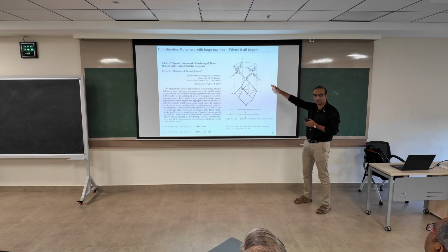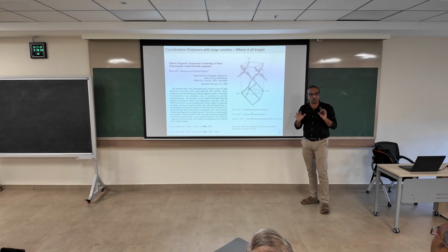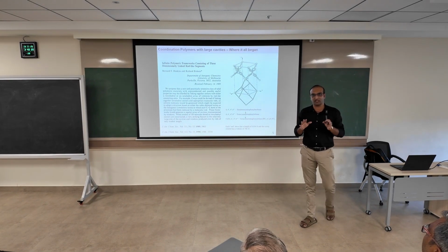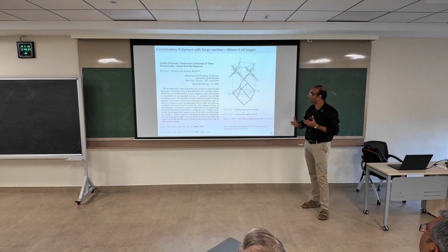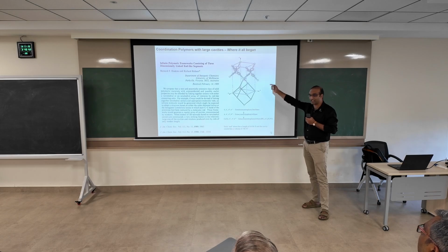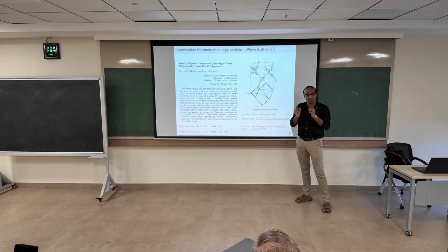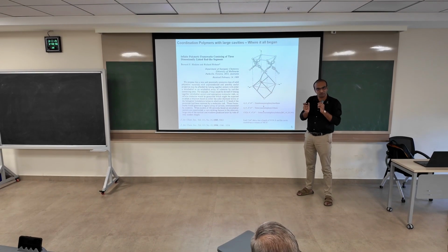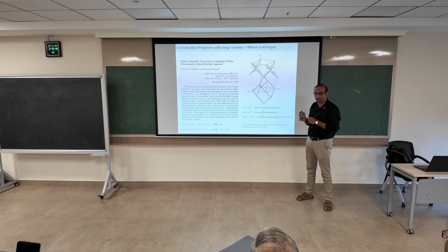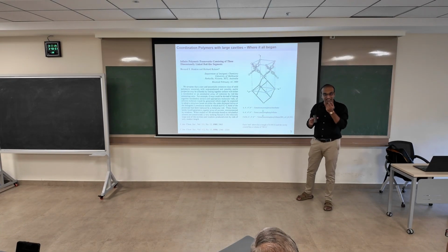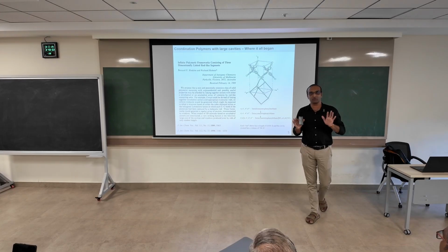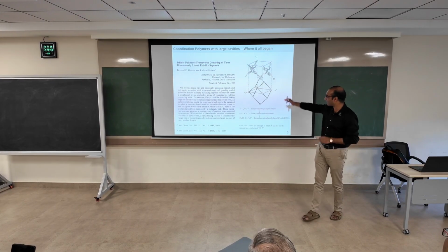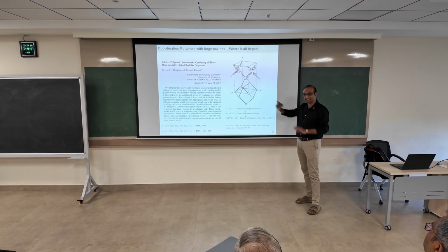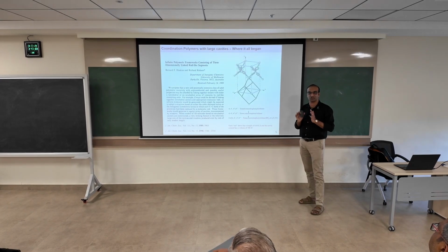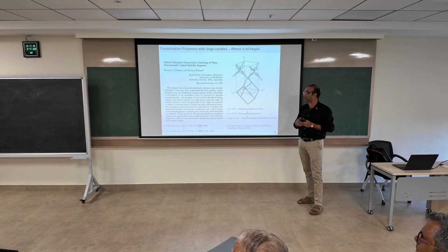And when you mix these compounds, very readily they form. You don't have to put too much temperature, or you don't have to put too many conditions for it to crystallize and form an extended solid. Okay, and you can change the amount of this that is there. If you don't put the right amount of this, you can probably get some defects in the structure. So if you put the correct molar ratio, the correct stoichiometry, you can get these extended compounds. You can get very fine crystals also, not requiring too much effort to make these. Some of them happen at room temperature itself. Okay, it's just coordination compounds, but now you have structural order that you would not have seen before.